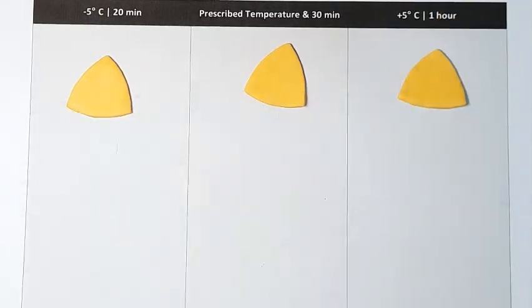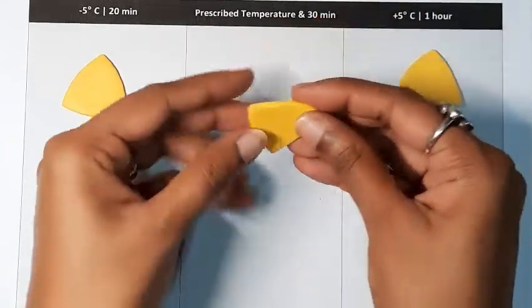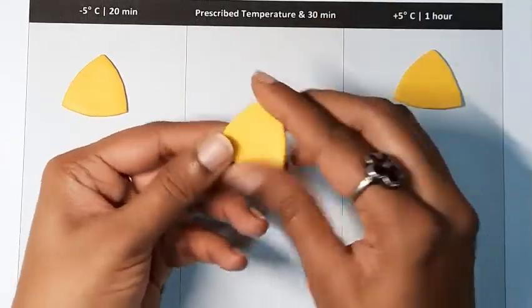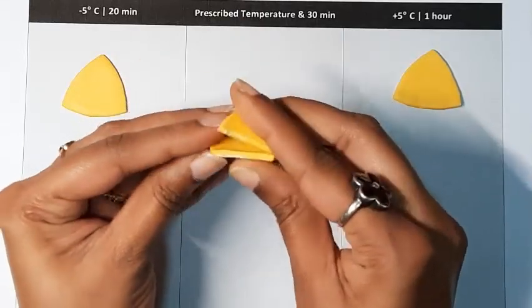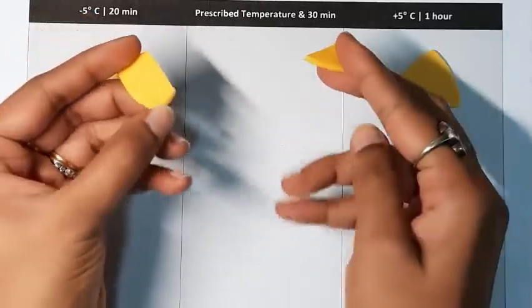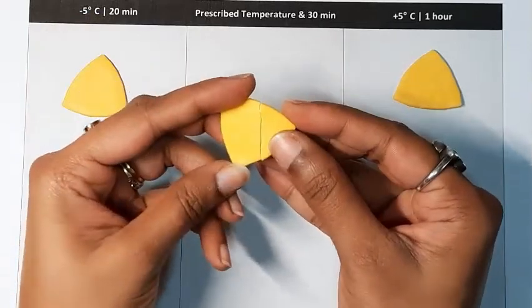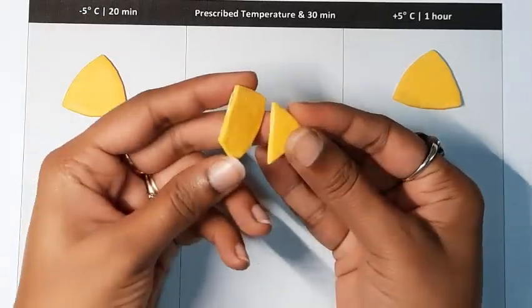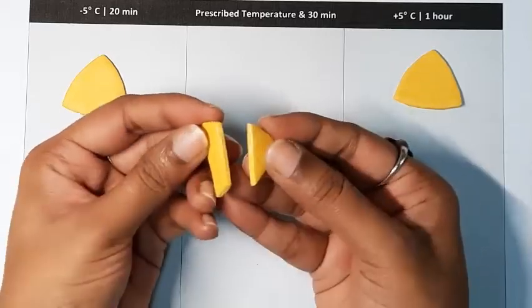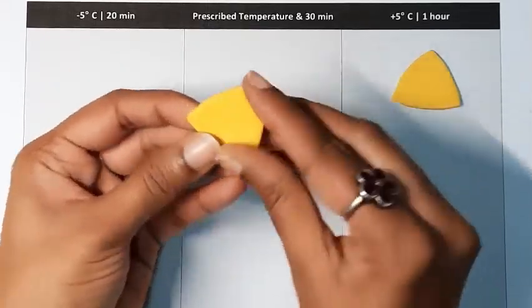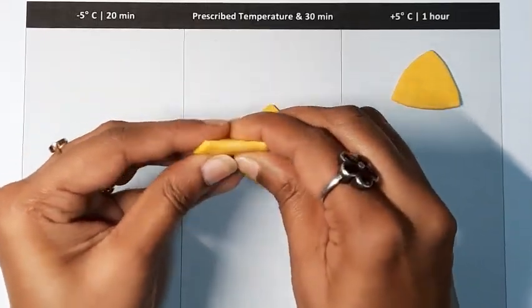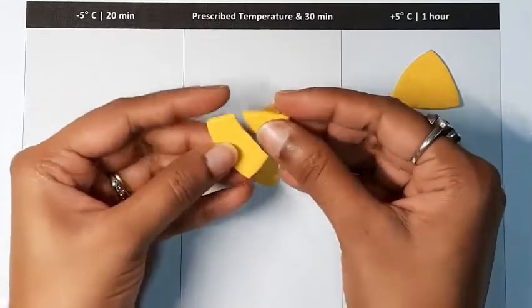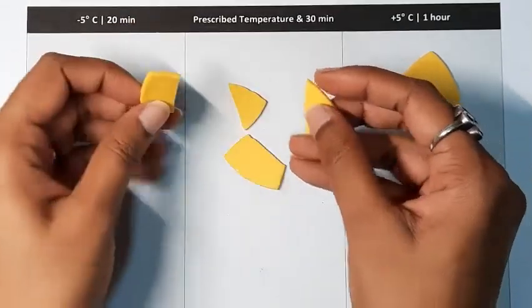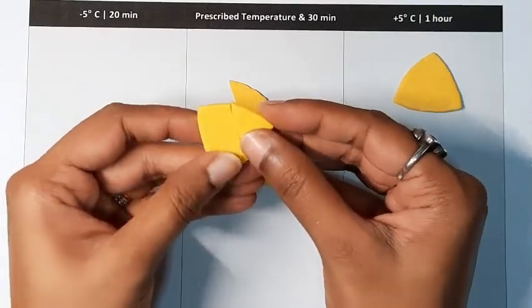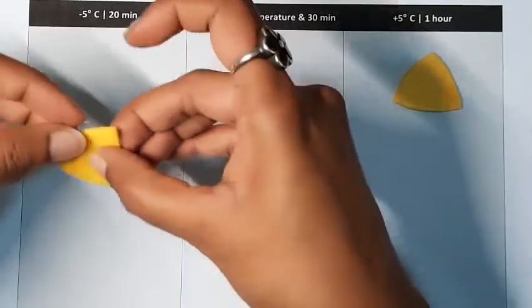I'll now check the pieces for strength. I'm assuming that this is not going to break as easily, but let's just check. Oh, so clearly this particular clay needs to be baked a little more because it just snapped. It did not even flex much. It just broke into two. And I'm assuming this will also have a similar result because it's not got the exact amount of time. This also breaks. This was expected. I was not expecting this to not break. This had to crack because it's not got the right amount of time and temperature.